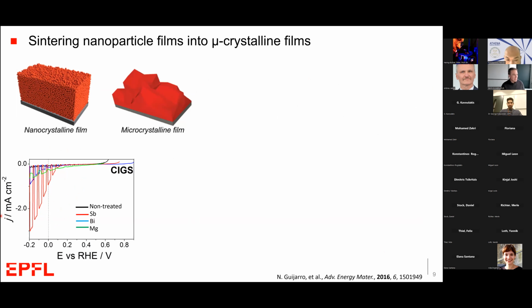So this is the first time that I've shown one of these LSV or linear scanning voltammetry curves. So I'll just take a second to explain it. On the x-axis here, we have the applied potential. So in the lab, we're testing one of these photoelectrodes at a time, and we hook it up to a potentiostat, we vary the potential, and we measure the photocurrent under intermittent illumination. So you can see the red curve here going up and down.